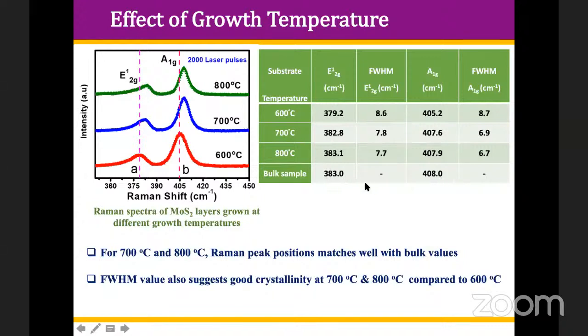In the literature, these two modes are obtained at 383 and 408. And these modes are quite close for the films deposited at 700 and 800 degrees centigrade. So 600 we have discarded. So we focus for future work on 700 and 800 degree temperature.